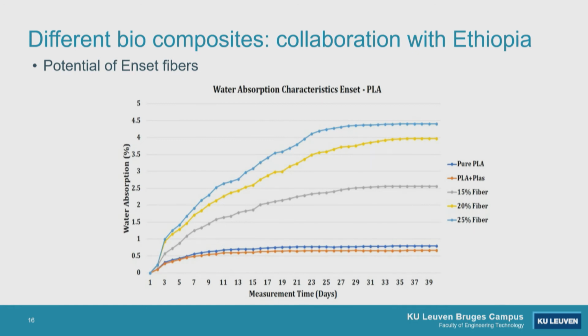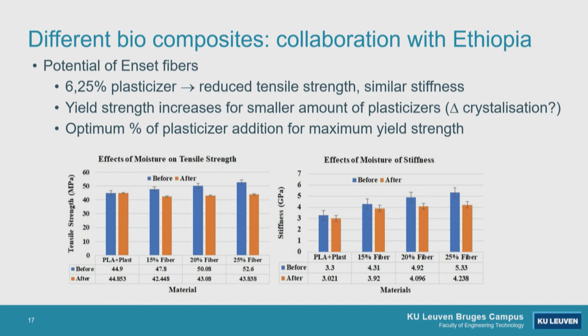Okay, so what is also checked is the water uptake as a function of time. If we have the pure PLA, we can compare it with the different amounts of fibers, and you can also see it's really sensitive to water or humidity. So what is the potential of this Enset fiber? You can look for an optimum percentage of plasticizer, depending on the application, and tune your combination. Also, as stated already before, adding all these additives or strange components into your PLA can also modify your crystallization behavior. So that's, of course, also influencing the whole behavior of your material.